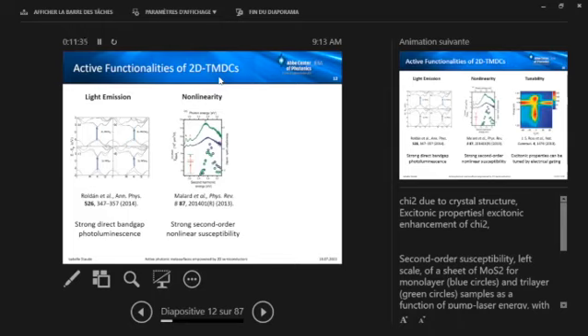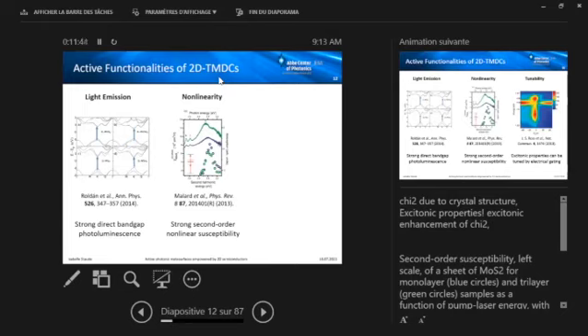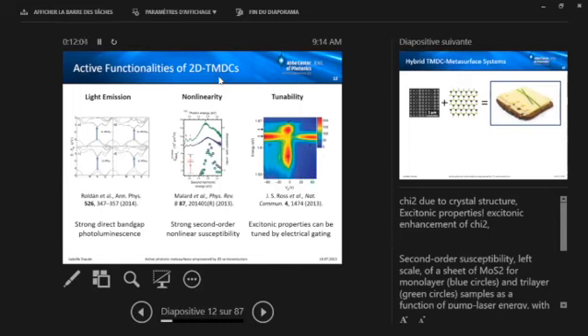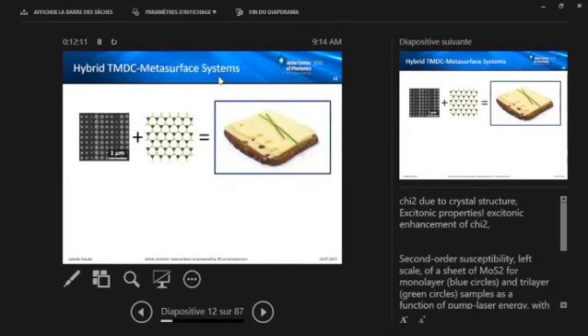And because they are so flat, the excitons are confined in 2D, and also screening is absent, so that the exciton binding in this material is very strong and is preserved at room temperature even, so that these effects, and also in particular the nonlinearities here, they are really enhanced by the excitonic resonances. And finally, because these effects are excitonically dominated, we can also easily tune this behavior, both the nonlinearity and also the light emission by electrically gating these materials. So we see we have all these categories we're interested in: light emission, nonlinear and tunability, we get from our 2D TMDCs.